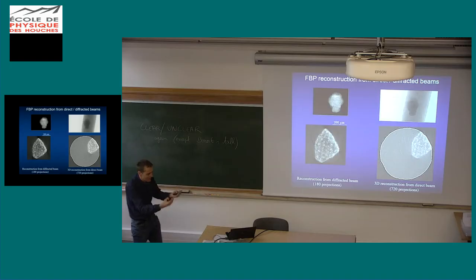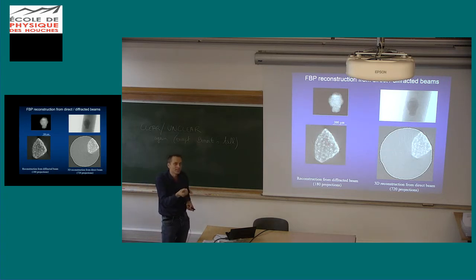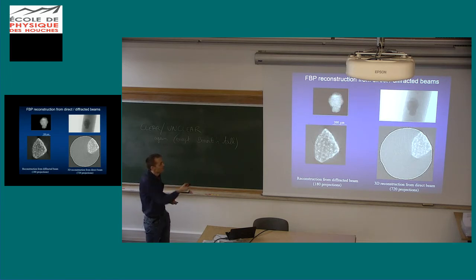So why it's interesting? Because you have at the same time absorption imaging. You can see, this is the absorption, a slice through the sample. It was an aluminum polycrystal, large grains. There are some iron-rich precipitates which you can kind of guess with these white dots. And you see them very well. Now this is the reconstruction, a slice through this grain, reconstructed, the outline of the grain boundary. This is the outer surface of the sample here. And you see these dots. This is the strain fields around inclusions that show up somehow in diffraction conditions. Very qualitative. They simply surface or they highlight the presence of some strain and particles inside. So it could be interesting to, well, pinning or things like this could possibly be watched at this length scale. But be aware it's at least one micrometer limited.